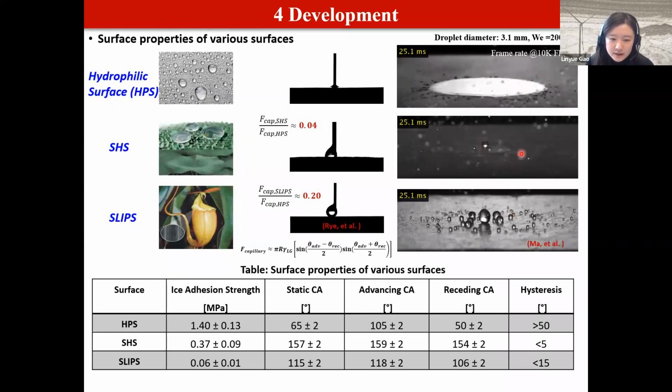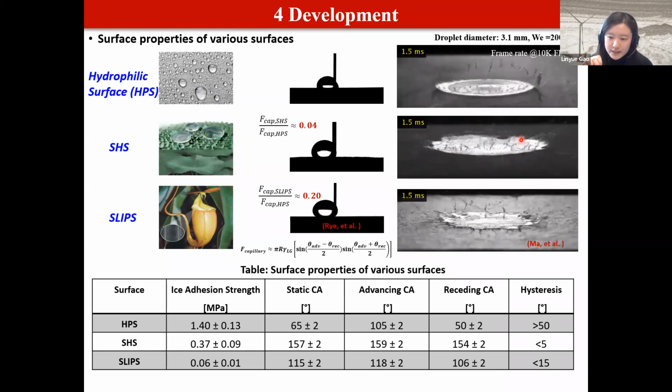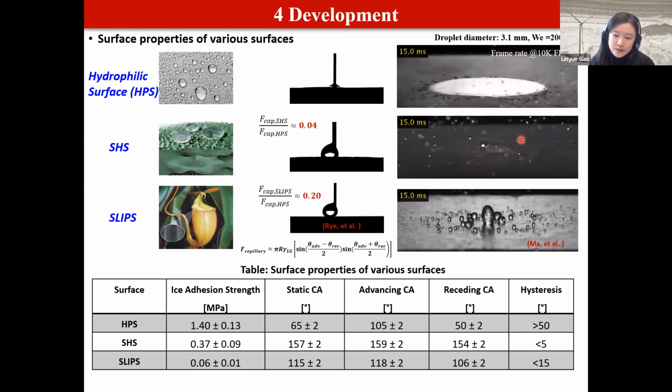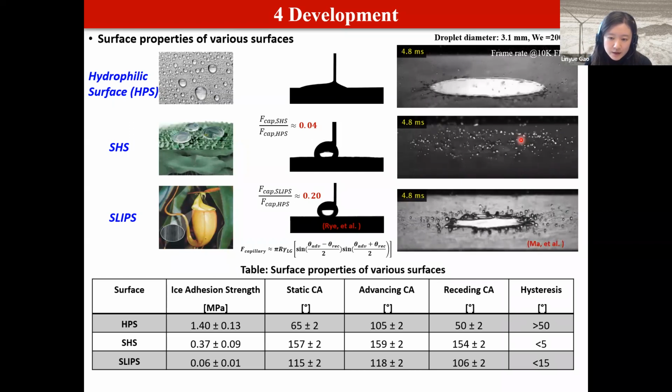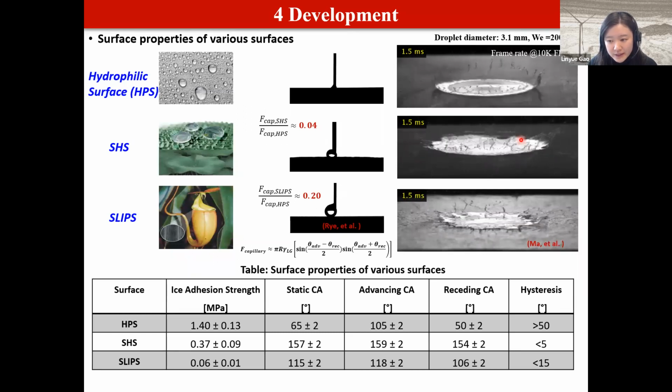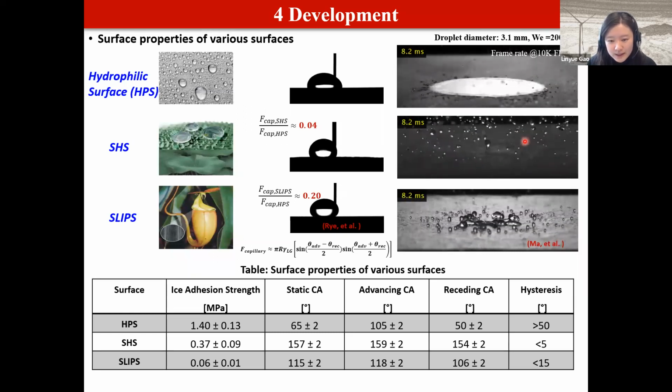And let's see the other two. After the water droplet impinges onto the superhydrophobic surface or the slip surface, we can see it spreads out rapidly to form a very thin water film over the impacted surface. However, instead of forming the pancake-like water film, the outspreading water film is found to break into many tiny droplets, bouncing off from the impacted surface immediately and splashing into the ambient air over the impacted surface.